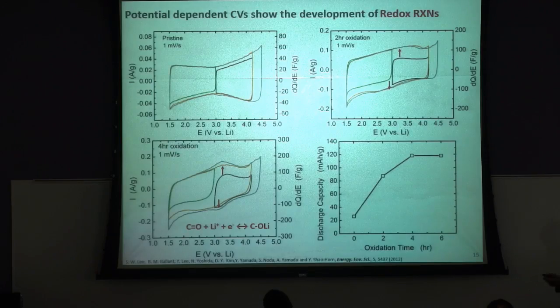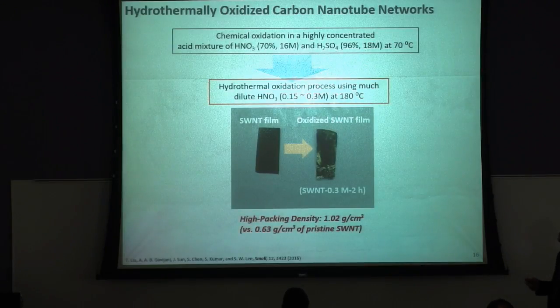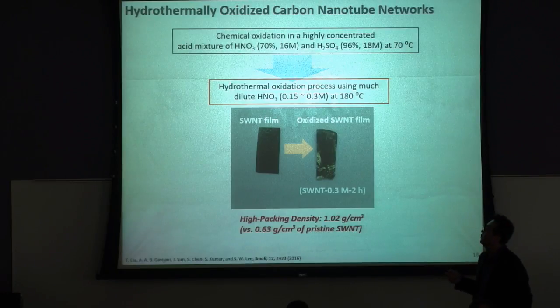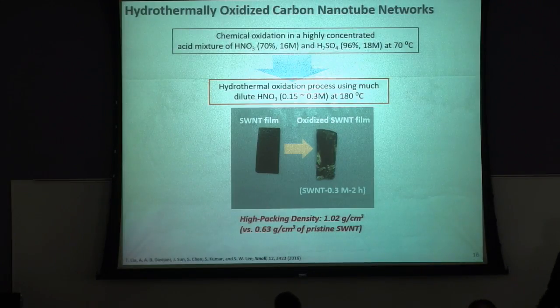For this kind of chemical oxidation process, we use a strong acid mixture, for example 70% nitric acid and 96% sulfuric acid. As you know, this kind of strong acid mixture can cause environmental and safety issues, right? To replace this process, we developed a new oxidation process using much more dilute nitric acid. The nitric acid concentration is around 0.15 to 0.3 molar. Instead of chemical refluxing, we apply a hydrothermal oxidation process.